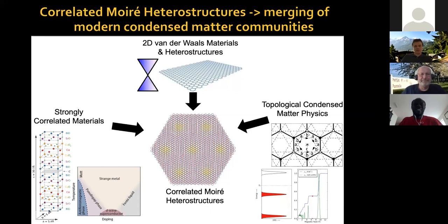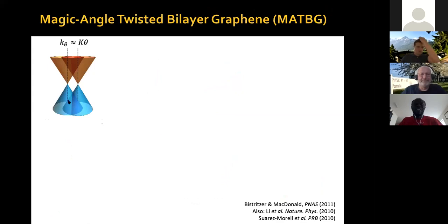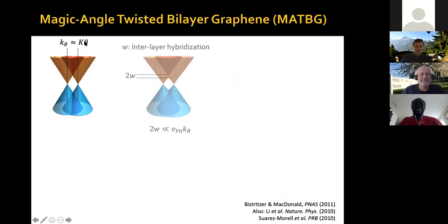And today I want to go and advance a little bit more. So just to remind everybody, if you have two sheets of graphene stacked on top of each other within a single particle picture and without interactions between hybrid, tunneling between the layers, this is what you get, two Dirac cones that interpenetrate each other. The separation between these Dirac points is proportional to the angle of rotation for small angles. If you count interlayer hybridization, then in reality, because the electrons can tunnel between the two sheets because they're only 3 angstroms apart, then a gap opens here.